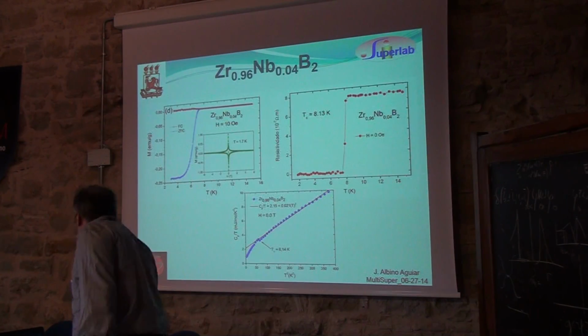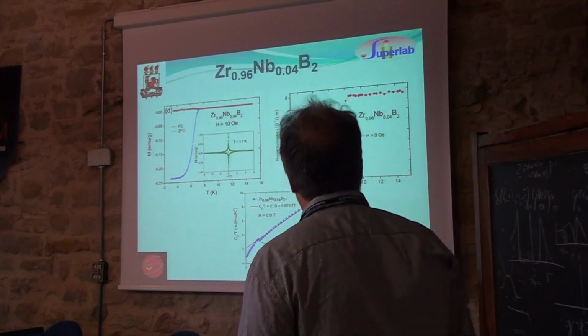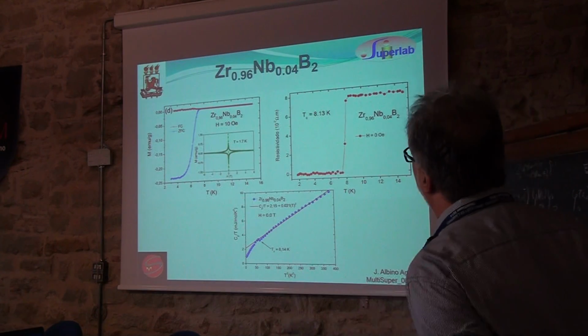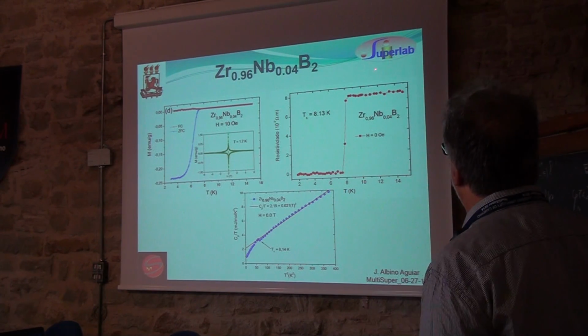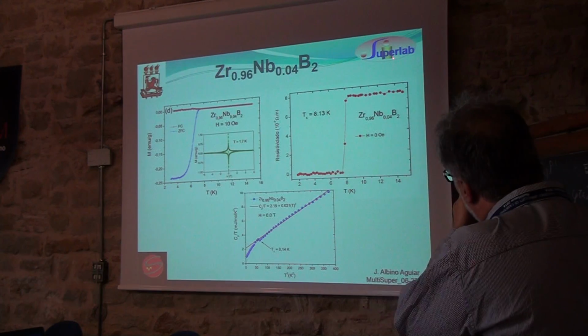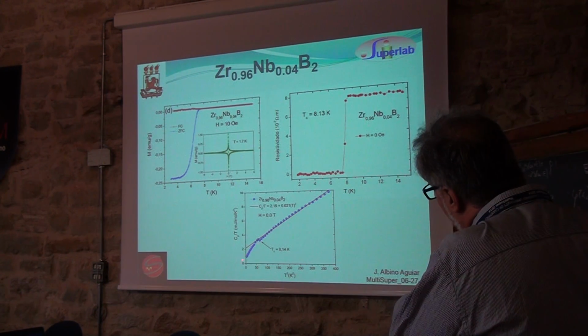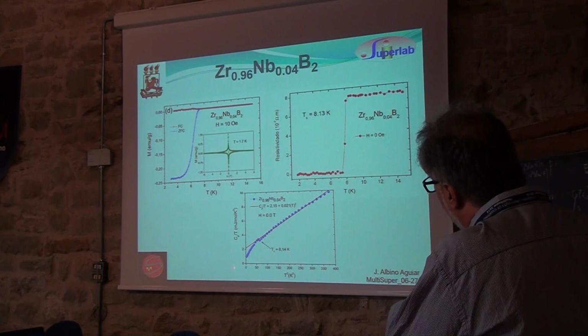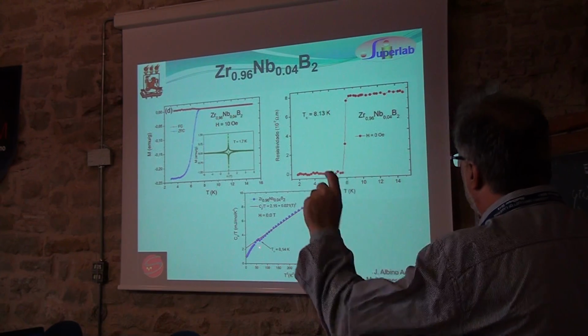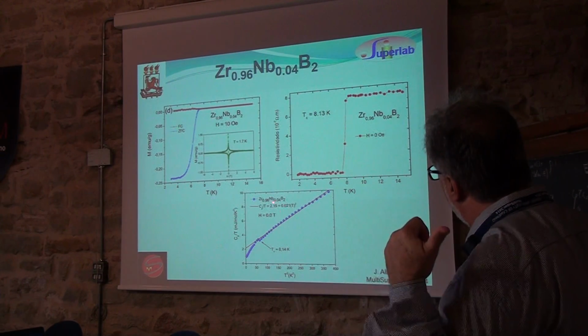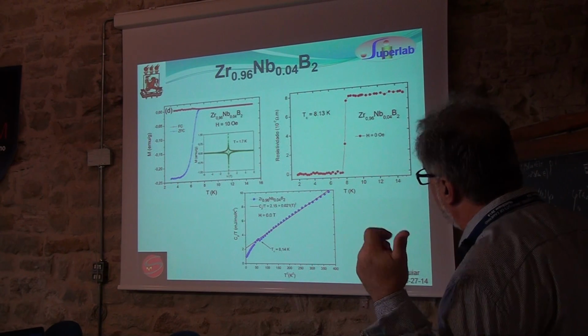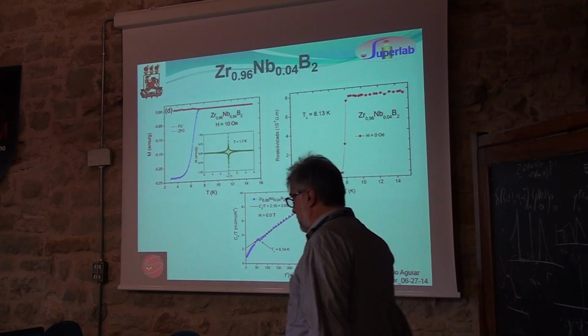I'm coming to the end. 3 minutes. I think I'll finish in one. So, the resistive transition at zero field and the heat capacity. You see that it's a smaller jump. For the other one with vanadium, we have for gamma 3.8, here it's 2.1.